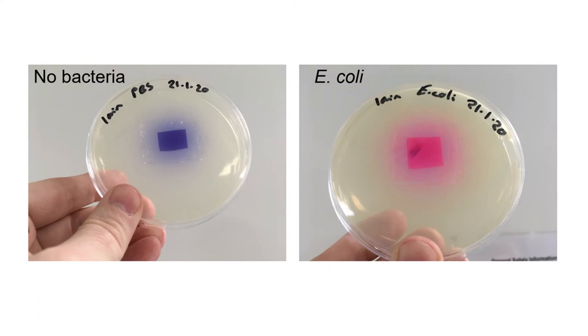The DERMA team was working on 2 versions of a diagnostic dressing using very similar materials. One, a film form based again on the use of plasticized agarose, and an electrospun fibrous version. But I will describe here the results of the agarose film form. So the films were tested against well-known problematic bacteria responsible for chronic wound infections, including Staph aureus, E. coli and Pseudomonas aeruginosa. And the presence of bacteria was indeed able to be detected by these films by way of a stark colour change from blue to fluorescent pink, caused by activation of the dye held within the film.